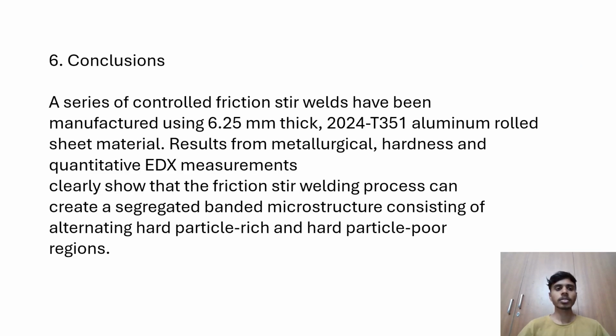Sixth, conclusion. A series of controlled friction stir welds have been manufactured using 6.25 mm thick 2024 T351 aluminum rolled sheet material. Results from hardness and EDX measurements clearly show that the friction stir welding process can create a segregated banded microstructure consisting of alternating hard particle rich and hard particle poor regions.